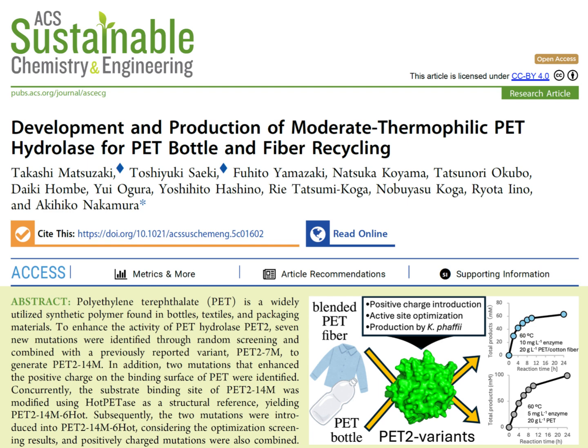Right. Here they found something really surprising. These blended fibers were only degraded effectively at 50 degrees Celsius by both enzymes. Only at 50, not higher. No. They specifically noted that degradation didn't work well at the higher temperatures they tested, like 60 or 70 degrees Celsius. That seems counterintuitive. Why would lower temperature be better? It puzzled them, too, initially.